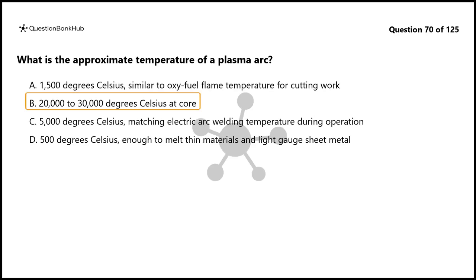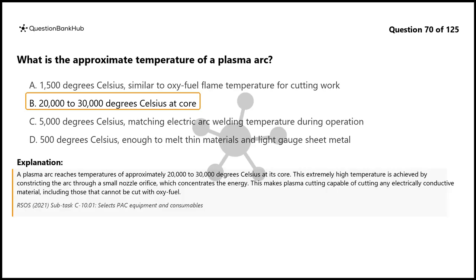The correct answer is B. 20,000 to 30,000 degrees Celsius at core. A plasma arc reaches temperatures of approximately 20,000 to 30,000 degrees Celsius at its core. This extremely high temperature is achieved by constricting the arc through a small nozzle orifice, which concentrates the energy. This makes plasma cutting capable of cutting any electrically conductive material, including those that cannot be cut with oxyfuel.